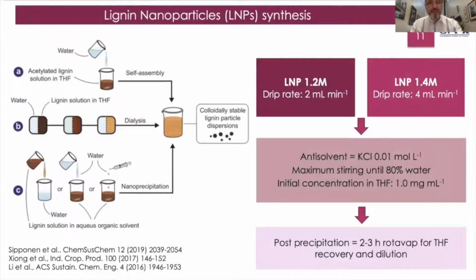For the preparation of the lignin nanoparticles, two different solvent dripping rates were utilized, 2 mL per minute and 4 mL per minute, and both coming from a solution of these lignins of 1 milligram per mL in THF. And the dripping of those two solutions, I mean, for each one of those cases, two different rates, was done over KCl 0.01 mole per liter as the anti-solvent. The lignin nanoparticles were then obtained as a suspension after removal of THF by evaporation.